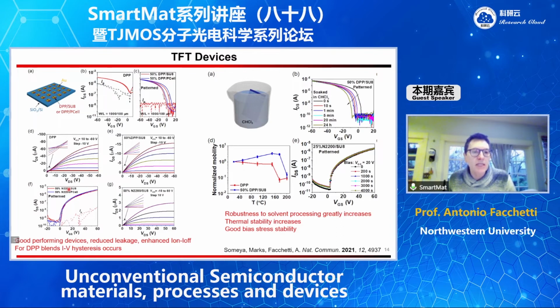If you photo pattern the N2200, the N-type polymer, here there is really no hysteresis, but these are quite well-behaving devices. So very good devices, which are very, very robust. We can take this TFT, immerse it into chloroform for 24 hours, and the device remains functional. You degrade in mobility, but I mean, you don't really need to put a TFT array into chloroform for 24 hours. So it just gives you a flavor of the robustness.